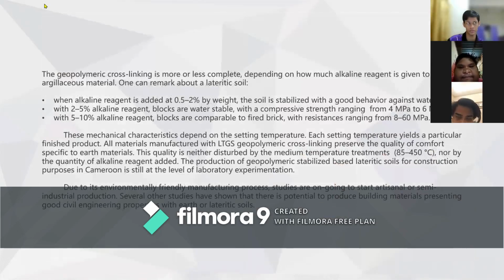So next, the geopolymeric cross-linking is more or less complete, depending on how much alkaline reagent is given to the argillaceous material. One can remark about a lateritic soil. When alkaline reagent is added at 0.5 to 2% by weight, the soil is stabilized with a good behavior against water. With 2 to 5% alkaline reagent, blocks are water stable with a compressive strength ranging from 4 MPa to 6 MPa. With 5 to 10% alkaline reagent, blocks are comparable to fired brick with a resistance ranging from 8 to 60 MPa.